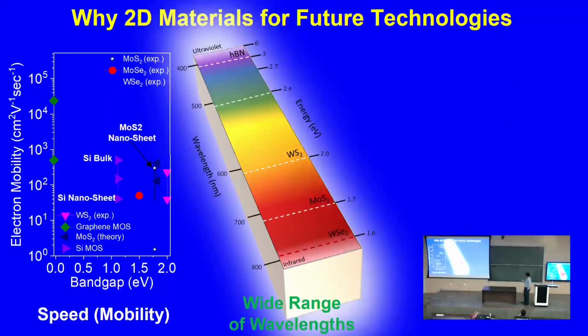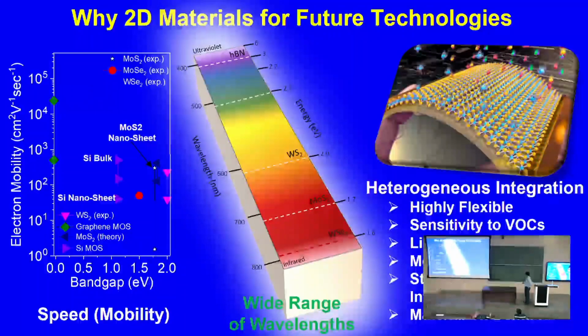Now on top of that, the TMDs or the 2D materials also offer you a very wide spectral range, right? So what is the advantage of this wide spectral range? You can basically use it for various optoelectronic applications. This was a limiting factor in bulk semiconductors, that you have possibly those limited band gaps available, so you have to tune or play around those band gap values. But with these 2D materials, depending on which material you choose, you have the entire range available from the infrared all the way to ultraviolet. So then you can use it for a range of optoelectronic applications with varying wavelengths required.